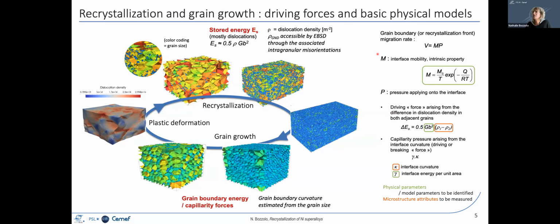So the grain boundary mobility is of prime importance. When a grain grows, actually the mechanism is the movement of its boundaries. So the mobility is one of the important material properties we have to deal with. And then we have also to describe the driving forces I've already mentioned, which are the stored energy contribution and the contribution of grain boundary energy. So you have here the expressions of the driving force associated with the difference in dislocation density. And here the expression of the driving force, which is also called capillarity force, which is actually related to the grain boundary energy.